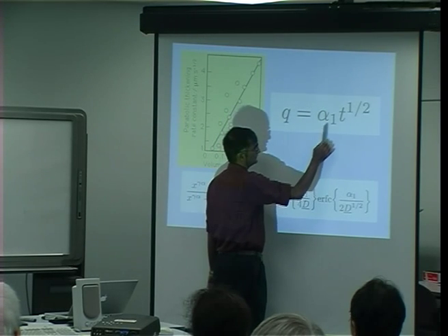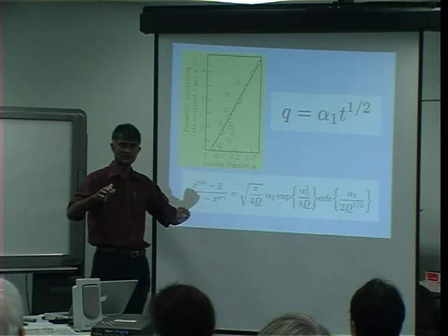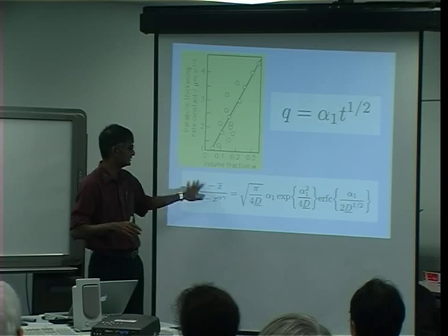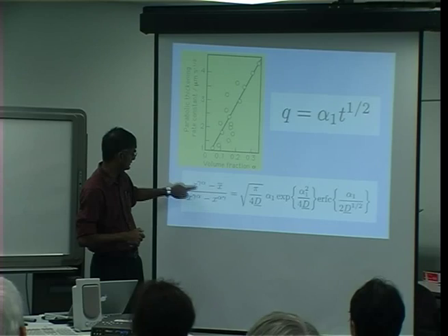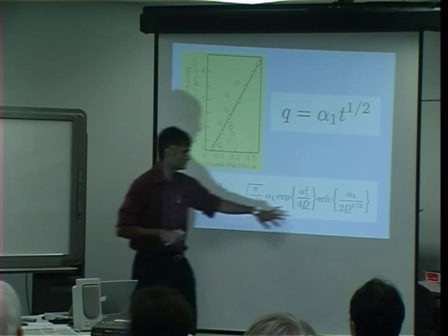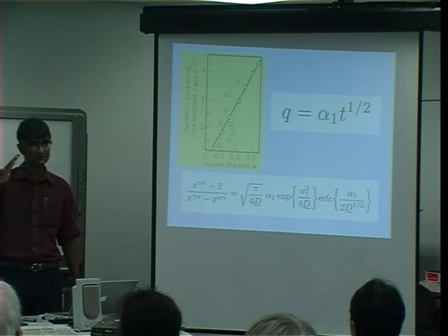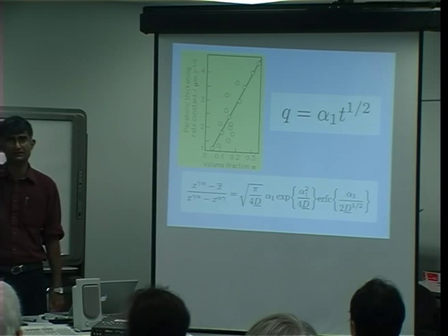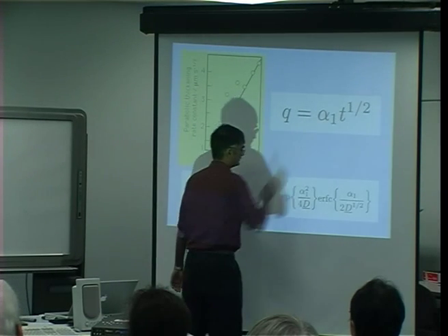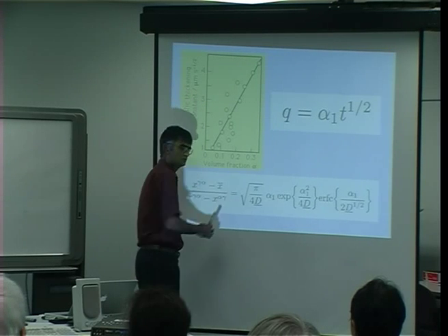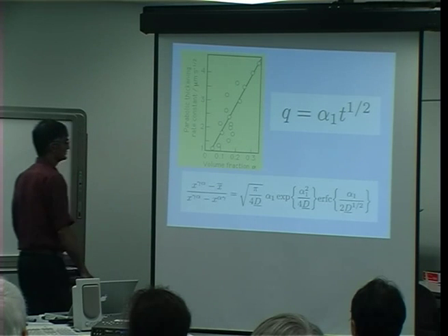So the growth rate then relies on this parabolic thickening rate constant, alpha 1, for which this morning I gave you an approximate analysis. You remember we had the concentration terms: the average carbon concentration in your material, solubility in austenite, solubility in ferrite. And this equation looks a little bit more complicated simply because I didn't assume that the concentration gradient is constant. It actually varies like an error function. But it doesn't change the essence of anything. We still have thickness varying with time to the half. And we have a concentration-dependent diffusion coefficient now. But again, the essence of the problem doesn't change.